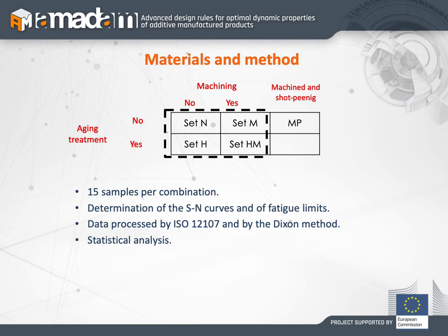And therefore we can combine all together. We have to consider that for all these kinds of tests, the micro shot peening has been applied, but in the case of machining, the peening is applied before machining the specimen.